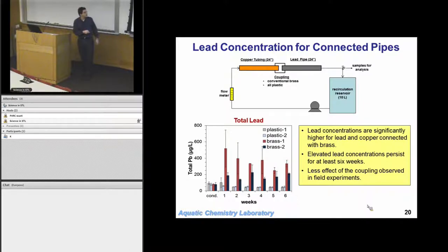So clearly, we had more lead release when we had the brass coupling, which allowed galvanic corrosion. The plastic was much, much better. And in fact, it was better than when we had the full lead pipe. So it was really not half as bad, but it was definitely better if we could avoid the galvanic corrosion. Maybe things were getting better with time. We did this for 6 weeks. If you did this for a year, there's some field studies that would say that it would probably have actually settled down and passivated at that point. But this, I think, should give us some cause for concern.